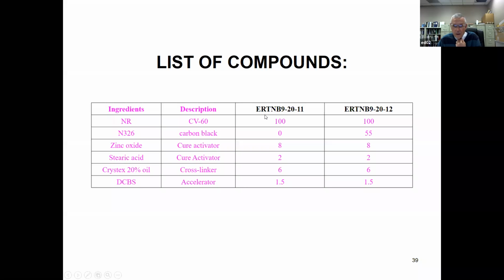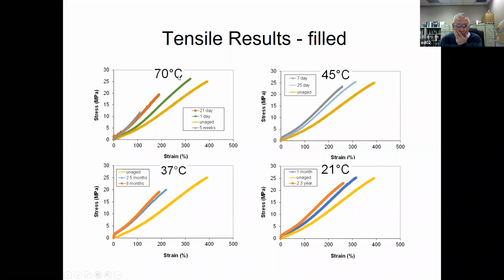So we lab mixed these two compounds. This is natural rubber conventional cure, unfilled, and then here's a lab mix conventional cure with carbon black filler. So we have unfilled and filled model compounds. Okay, so here are the tensile results of the filled compounds before and after aging: 70 degrees, 45 degrees,